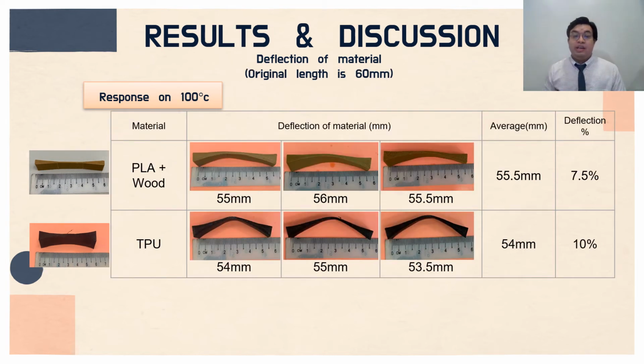For the 100-degree heat treatment, the specimens showed more deflection, which is 4.5 mm average for PLA plus wood and 6 mm average for TPU. And it showed 7.5% deflection for the PLA plus wood and 10% deflection for the TPU.